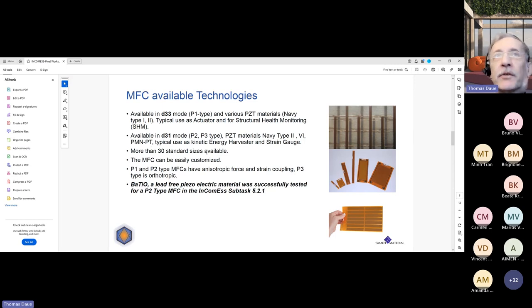We have more than 30 standard sizes available out of inventory, but more than 50% of all products are customized, so we can customize the sizes very quickly. What most of you have seen during the work packages, the P1 and P2 are anisotropic, so they have a preferred force coupling direction, normally along the long direction. And the P3 is more orthotropic, but not as flexible.